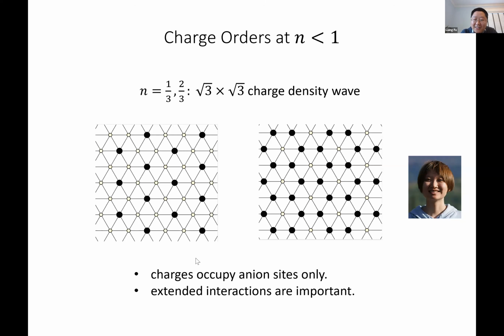In this case, the charges only occupy the anion sites. The system we're dealing with is the honeycomb lattice with two sublattices, right? The one that has a lower on-site energy, we call that anion, and when the filling is less than 1, all the charges go to these anion sites. So that's why here I'm only showing the triangular sublattice of the honeycomb.